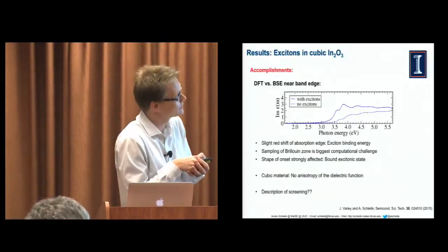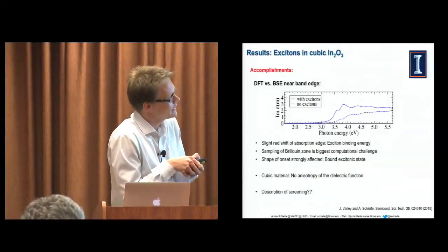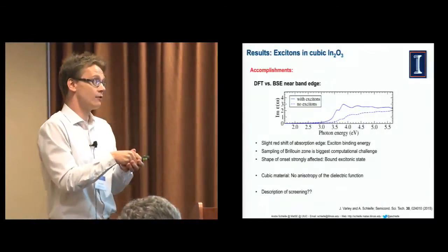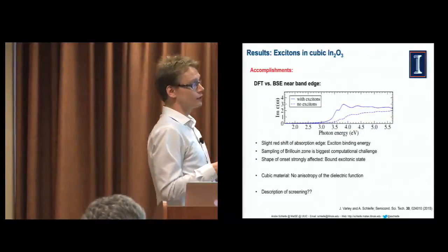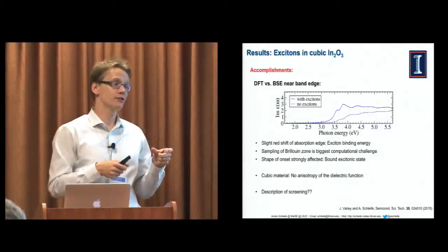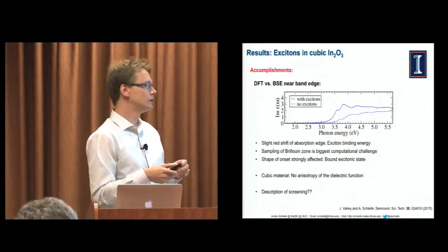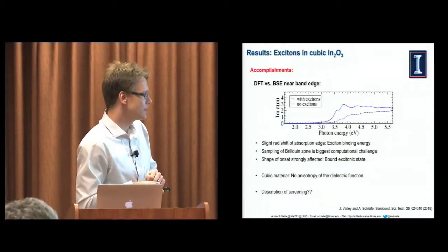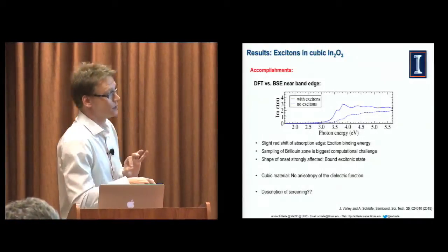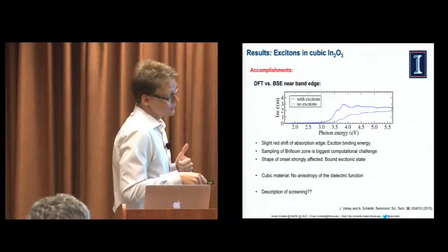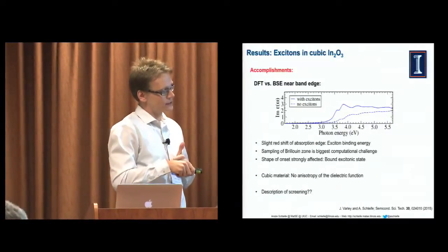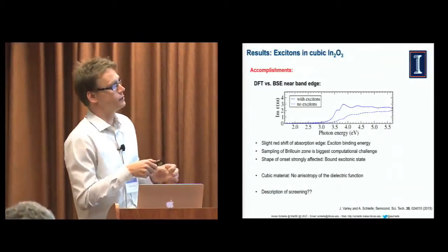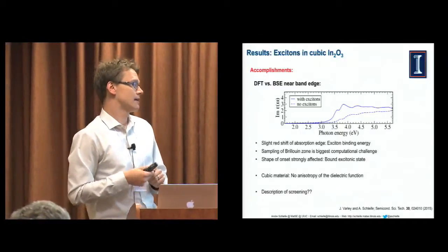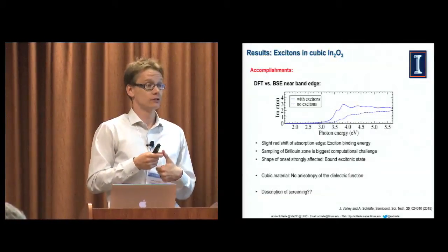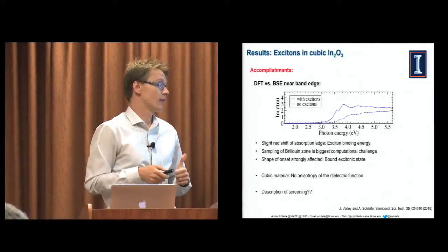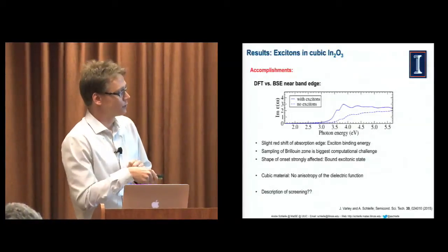The other thing you see is the onset position shifts a little bit. This is related to so-called exciton binding energy. That is something we have actually not fully converged in this calculation. So the binding energy makes it even more complicated to converge. And then this material is cubic, so there will be no anisotropy. The open question in this case is, how can we really describe this dielectric screening? In this case, we simply used a model dielectric function, but that is something that we expect to not be adequate necessarily for all energies and all frequencies. So we are looking into that in the future.